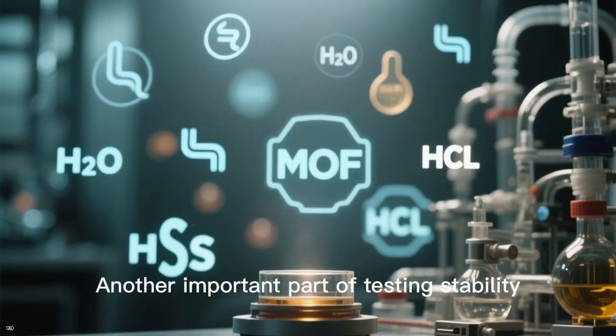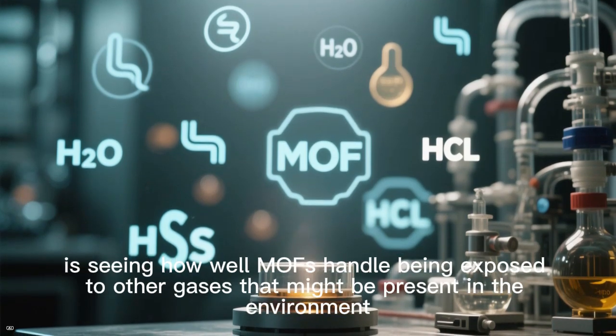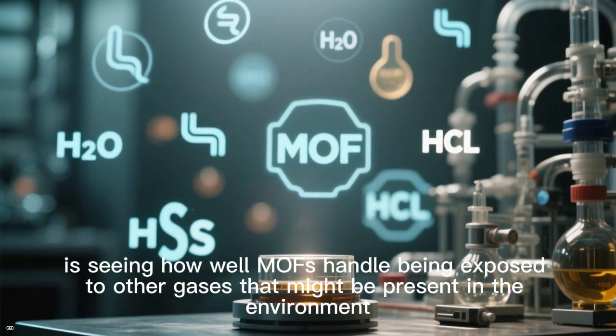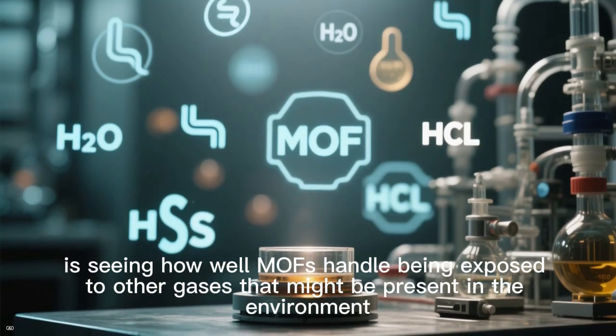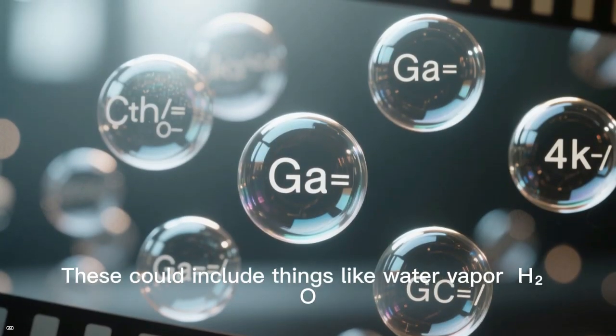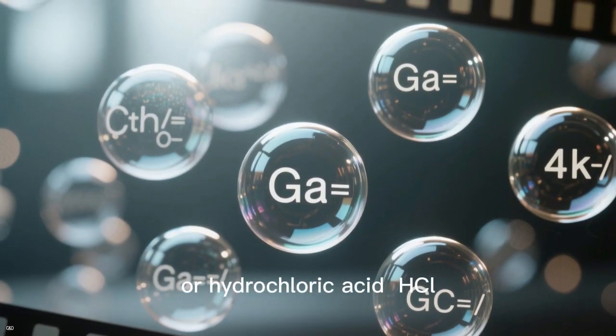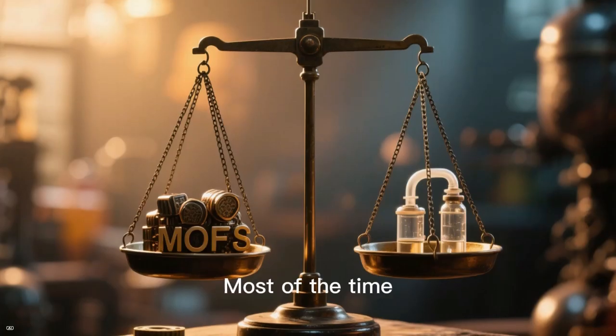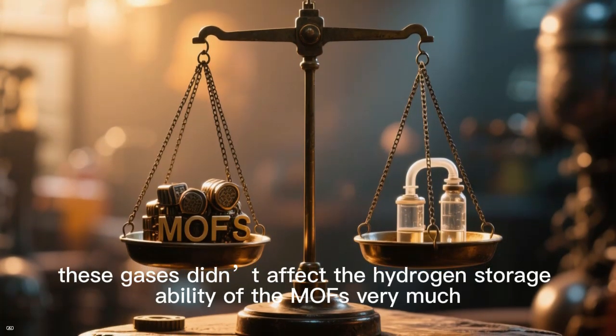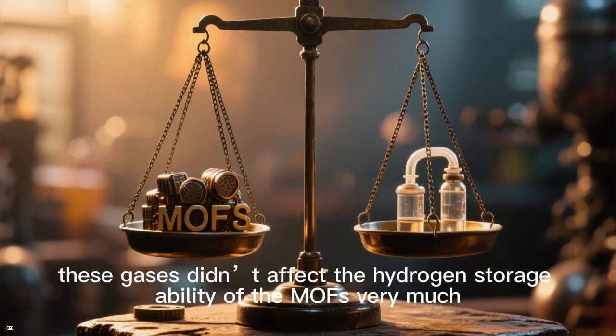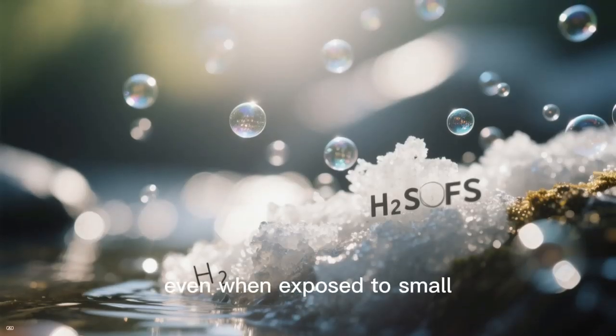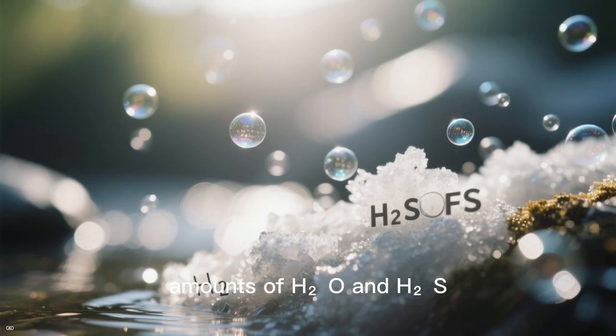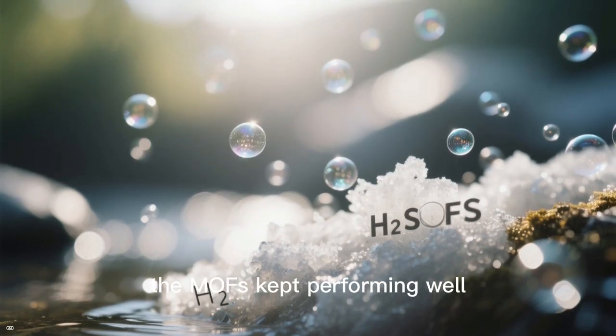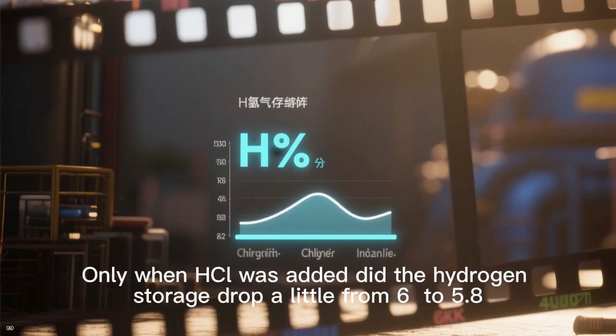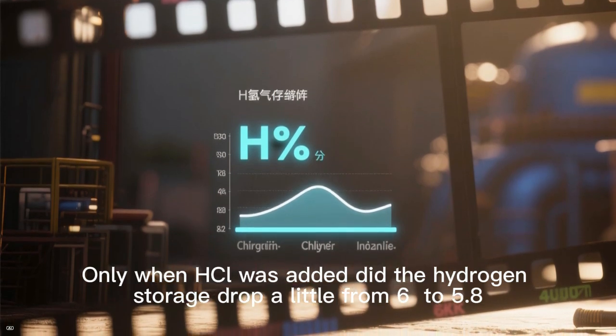Another important part of testing stability is seeing how well MOFs handle being exposed to other gases that might be present in the environment. These could include things like water vapor, H2O, hydrogen sulfide, H2S, or hydrochloric acid, HCl. Most of the time, these gases didn't affect the hydrogen storage ability of the MOFs very much. For example, even when exposed to small amounts of H2O and H2S, the MOFs kept performing well. Only when HCl was added did the hydrogen storage drop a little from 6% to 5.8% by weight, which is still a small change.